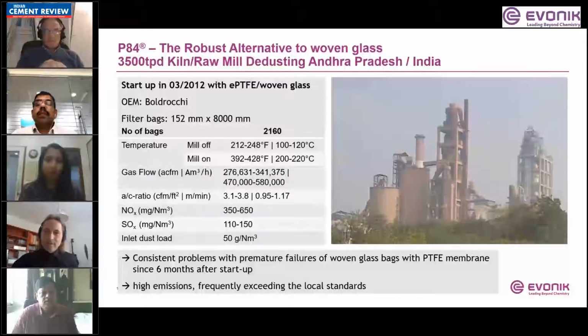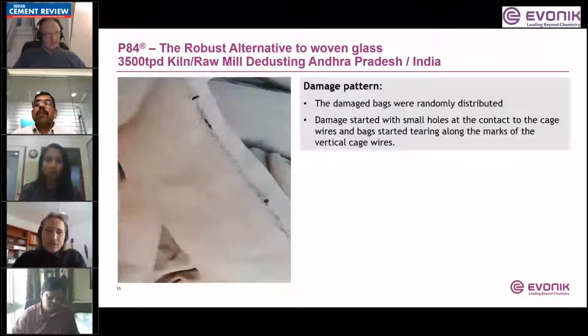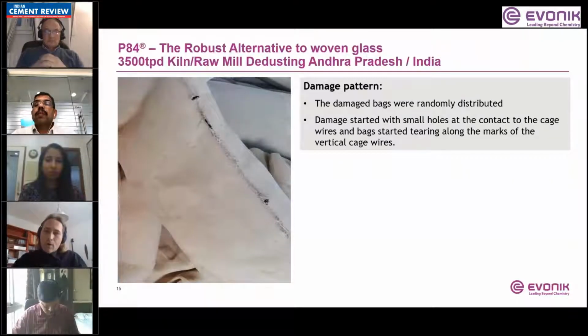regardless of which supplier, it was obviously related simply to the material quality, woven glass, which was not suitable for the conditions in this plant. The damage pattern looks quite similar in most cases with woven glass, since it's in most cases a mechanical damage. It's starting at the contact point to the cage wires, either because the membrane starts delaminating because of the mechanical stress there, or because abrasion starts from inside. The result is the same.